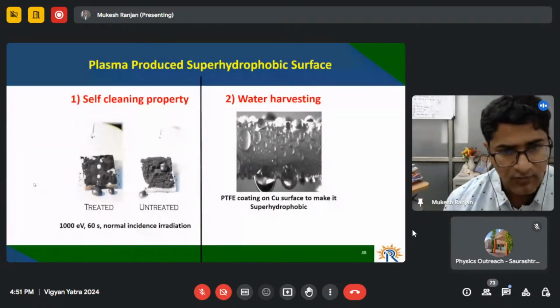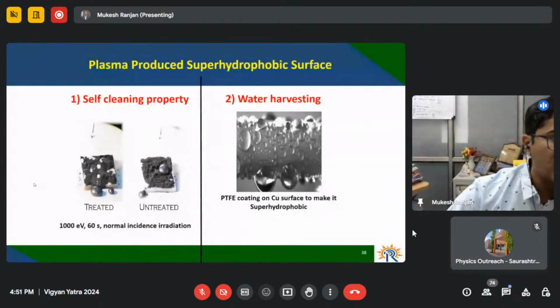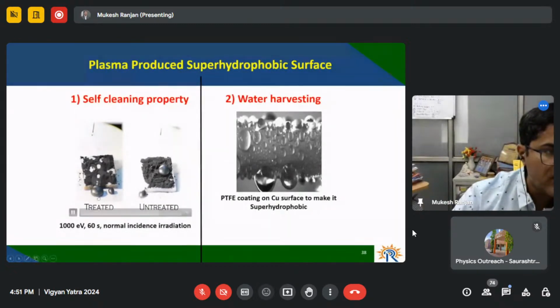So when you wash it, you will see that the surface will clean much better than the normal process. So this is what is shown in this movie. The first sample is the treated one, and the second sample is the untreated one. In the first case, you can see that the dust is not sticking to the surface, it is rolling with